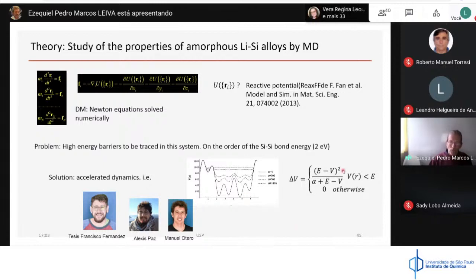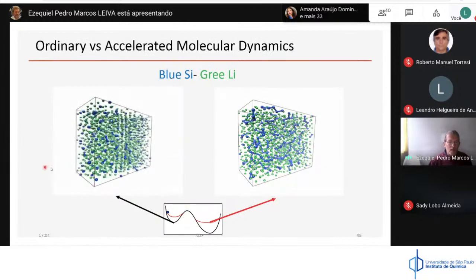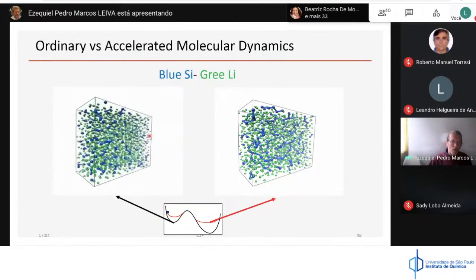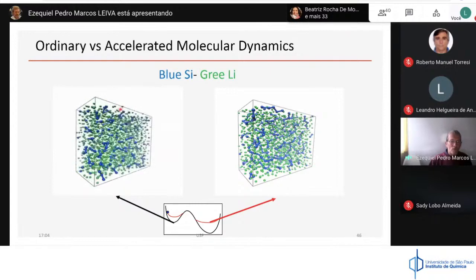So if you look at the original shape of this material, this may look like this, with huge energy barriers that you will not be able to overcome just by integration. But if you modify this energy landscape, you will move the system much faster. As an example, I show you on the left an ordinary molecular dynamics. That is, you solve the Newton equations for these systems.